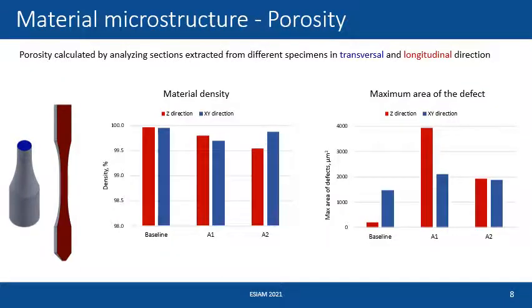The same trend is confirmed by the measurement that we carried out on different sections of three specimens for each set of process parameters. We see that while in the baseline condition the material density is almost 100%, both in longitudinal and transversal direction, when we increase the productivity rate, the material density tends to decrease until 99.5% for the A2 parameters